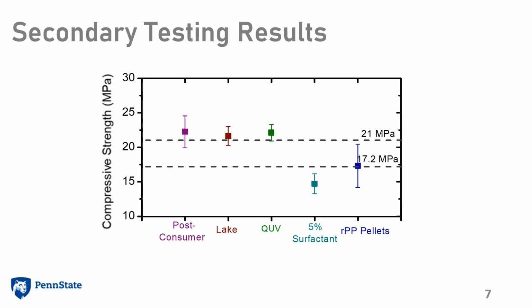Once the initial testing confirmed that a 28% loading level achieved the recommended strength value, several secondary tests were run. The first involved lake plastic to see if environmental exposure had any effect on the compressive strength. As seen in this graph, there was not a major change from the previously used post-consumer plastic. Plastic was also exposed to UV light in a QUV machine in an attempt to radicalize and oxidize the plastic in order to have some interaction with the polar cement. This also did not have a major effect, likely due to limited exposure time.